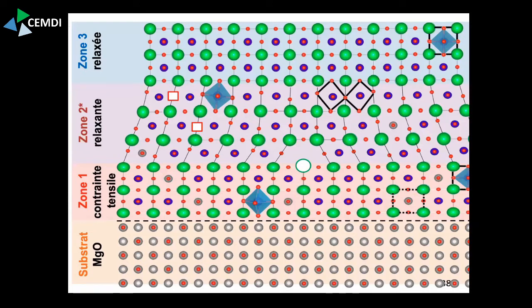What we have here is a cross-section of our film. So this is a side view across the film. We have the substrate at the bottom, which is our magnesium oxide. And on top, we grow strontium titanate. In the beginning, strontium titanate will beautifully adapt the lattice parameter. You can think of this like Velcro, or really like pressing one Lego on the other. And there will be a lot of elastic energy stored in this layer. And you build a second layer on top, and it will still adapt the lattice spacing from the underlying layer. It's epitaxial growth. But with this increasing elastic energy, the total energy of the system diverges with each layer that you build on top. It doesn't go well for very long.